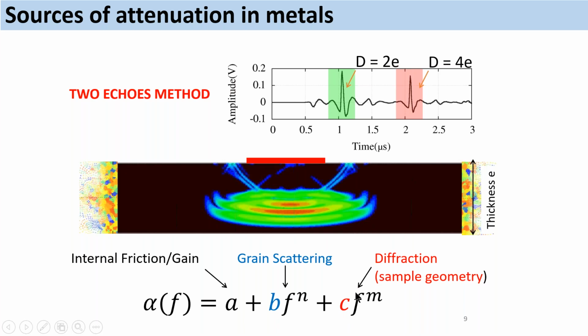And the third contribution is due to the geometry of the specimen and simply represents the dispersion of the wave, the diffraction of the wave inside the sample as it propagates through the sample. So you see here, if we were to measure the attenuation using 2 echoes, that is to say the ratio between the amplitude of this echo and this echo, these 2 echoes have 2 different propagation distances. Therefore, this one has propagated twice as far as this one. And so we can consider that this diffraction contribution in this method will be different for this echo and this echo. Therefore, it's hard to measure attenuation in this method because we cannot extract only the grain scattering contribution.